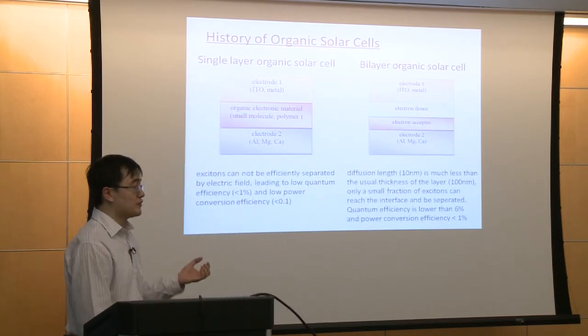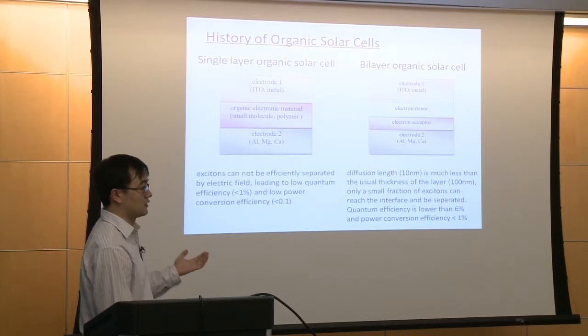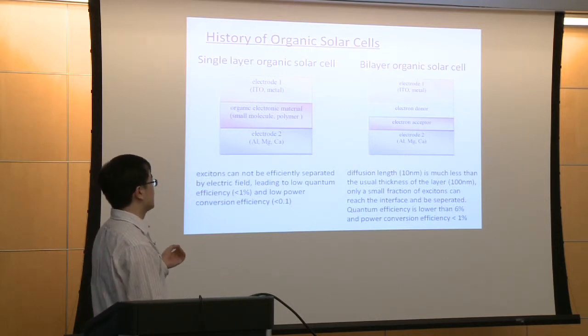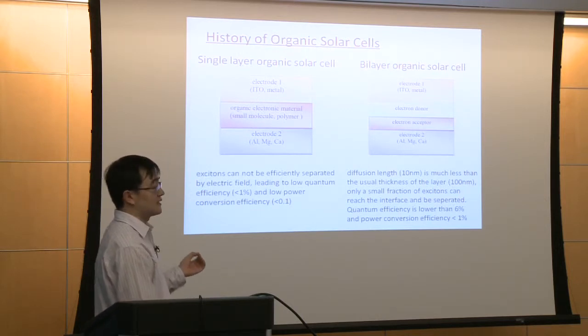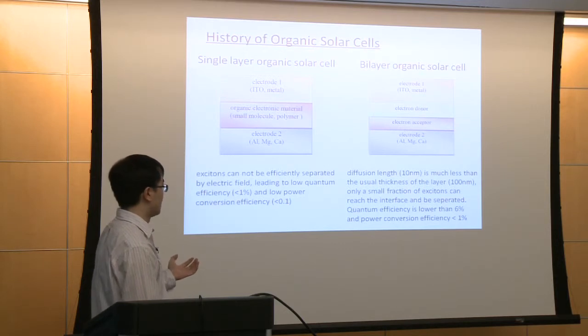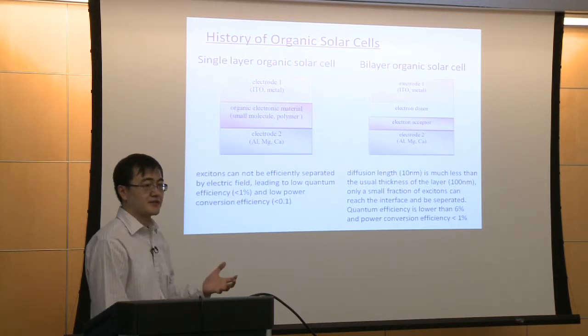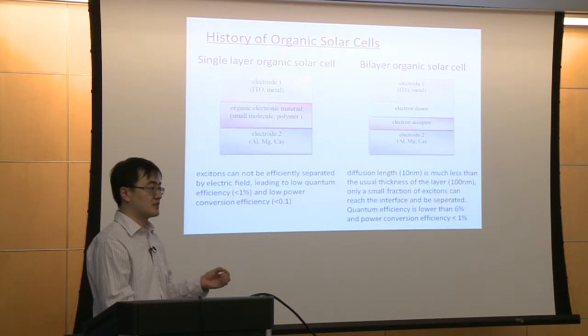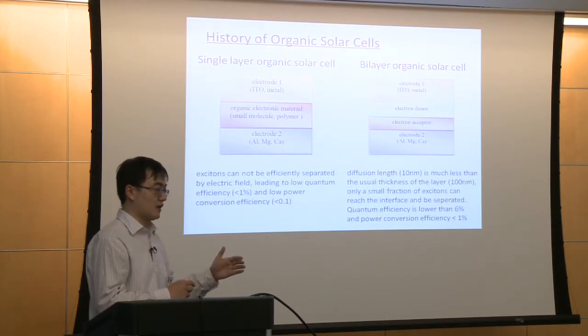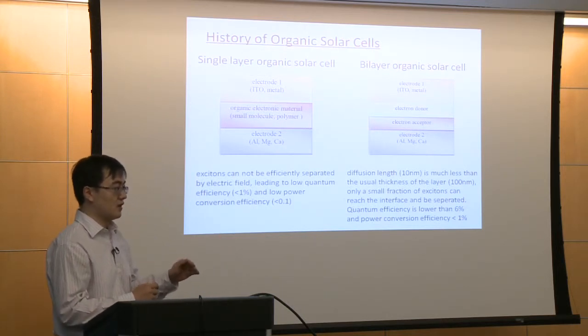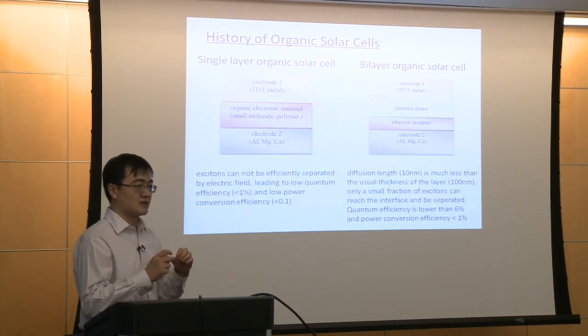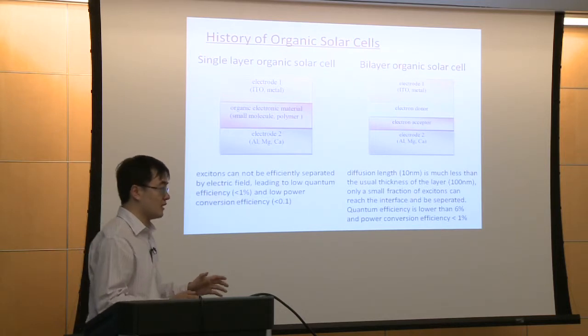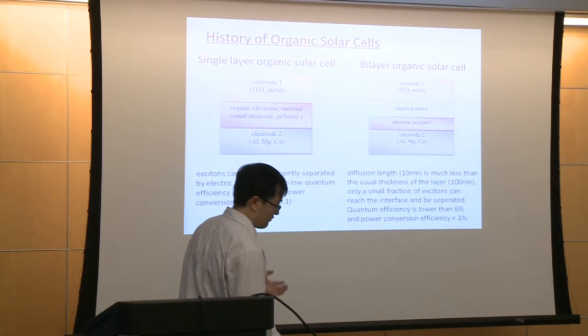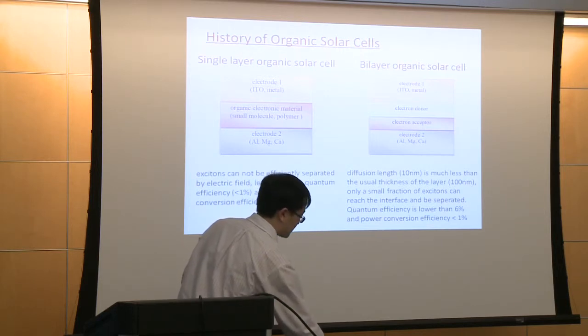because the diffusion length of the exciton is usually about 10 nanometers, it's much less than the usual thickness of the layer, which is about 100 nanometers. So only a small fraction of the excitons can reach the interface between the acceptor and the donor layer, which means just a small amount of the excitons can be efficiently separated. So the quantum efficiency is still very low, and the power conversion efficiency is less than 1%.